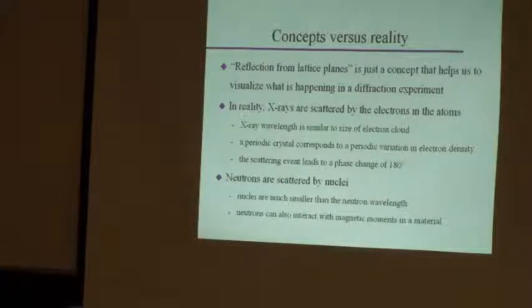And of course, atoms contain electrons, which means they are scattered by the electron cloud around the atoms. The reason for that is X-rays have a wavelength that is pretty similar to the size of the atoms, right? Angstroms. That matches. Interatomic distances are in the angstrom range. We might give them in a few hundred picometers, but that's the same as a couple of angstroms.